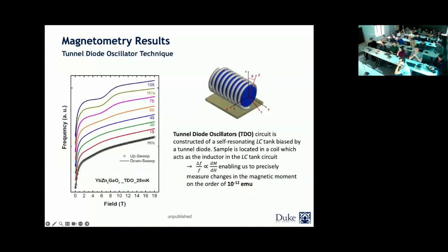The way that it works is that you have a coil, the sample sits in the coil, and it's connected to an LC circuit. Then we look at the resonance frequency of the coil. It's a very high resolution, even higher than SQUID. Through that, you can start to look at the change of the magnetization, because a change of the magnetization changes L, and when L changes, the resonance frequency of this coil changes. So by looking at the change of the frequency, you're indirectly plotting dM/dH.